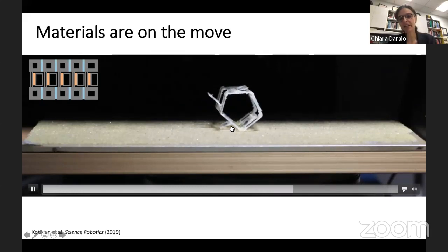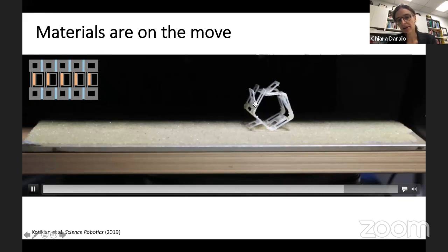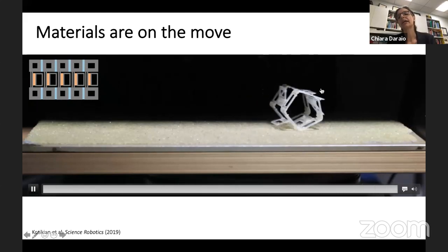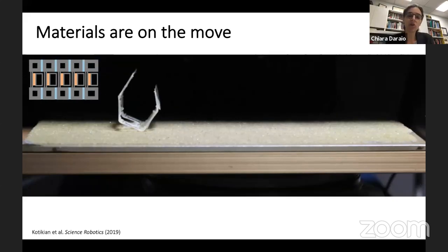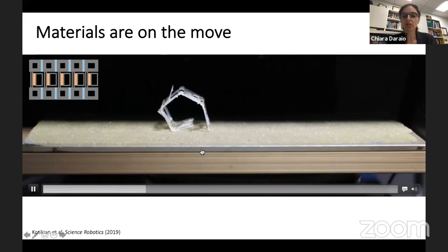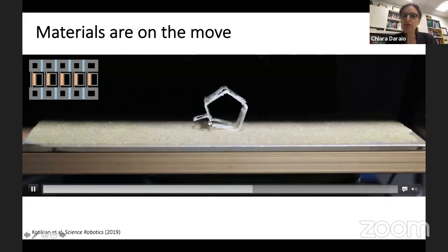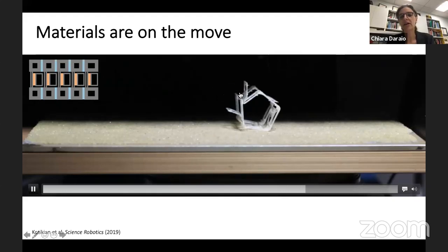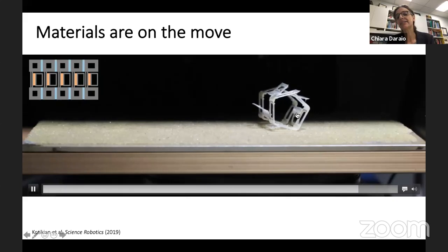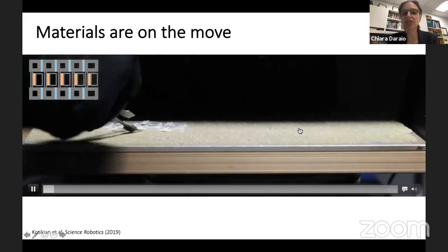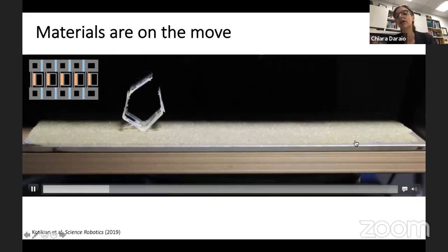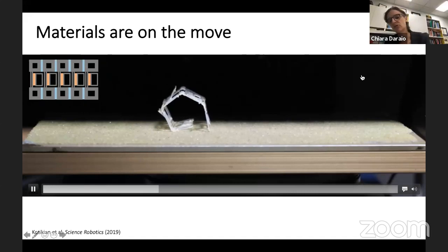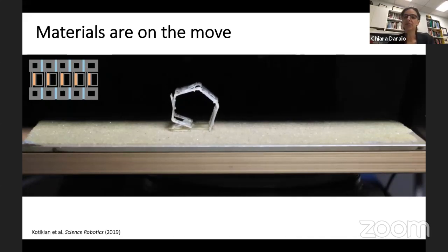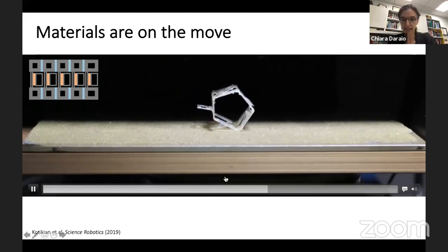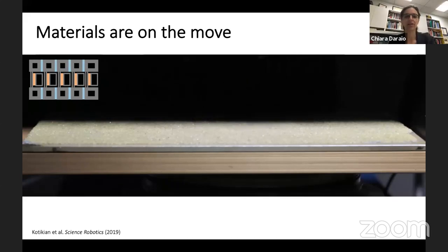And then slowly and steadily, the orange LCE or these other linkages here are actuated so that this object keeps rolling. Now, why does the object keep rolling? There is a clever mechanism in this case: you have a hot surface here, but the air up here is at room temperature. So although you can see these little flappers that look like little legs are actuated, once these little legs reach the top, they cool and hence they fold back. And this enables this rotation or continuous motion that will perpetuate as long as this differential temperature between the hot plate and the room above is maintained. So in a way, you have a polymer that can move itself to different locations.